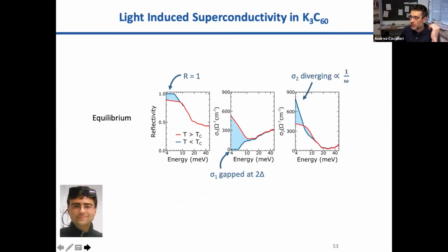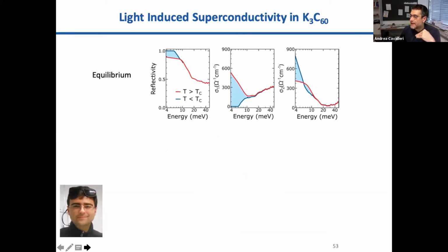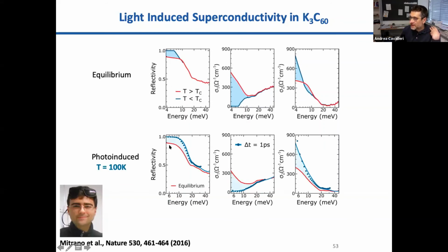And lo and behold, this is what I told you about before. This is the equilibrium features that I see if I cool the material below Tc. What Matteo did was to photoexcite the material above Tc, and he showed that, at 100 Kelvin, 5 times above Tc, by exciting one specific vibration of the material, he could obtain optical properties that are really very similar, by any standard that one can apply, to the ones observed when cooling below Tc.